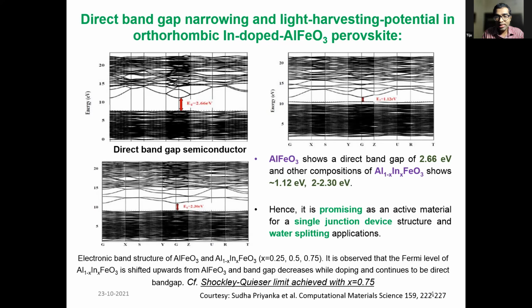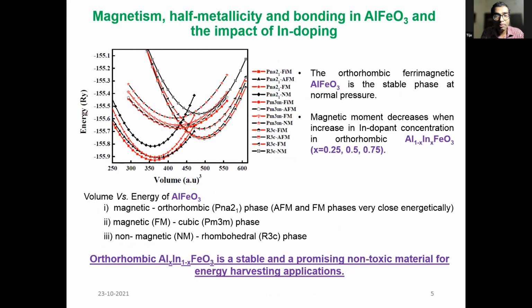And we were able to explore combinatorially, computationally, a few compositions. To begin with, it was data driven. Later on, it was driven by ab initio simulations. And we were able to predict that there are potentially some aluminum indium compositions out there, aluminum indium ferrite compositions to be more specific, which can offer Shockley-Queisser limits. Next slide, please.